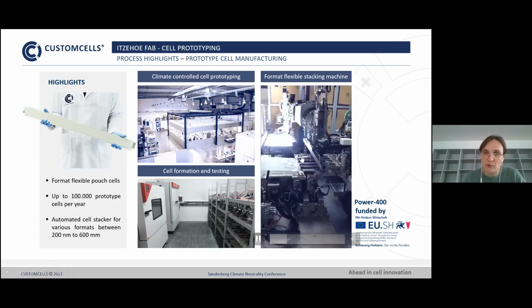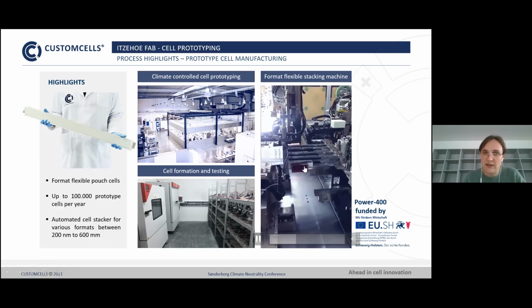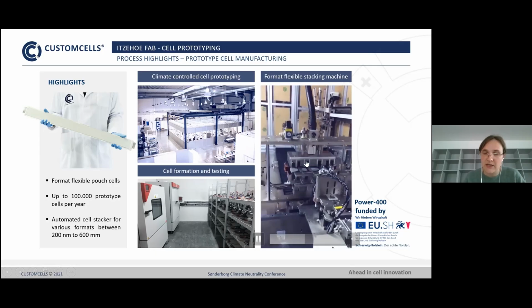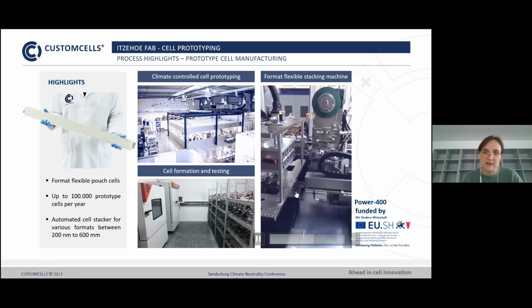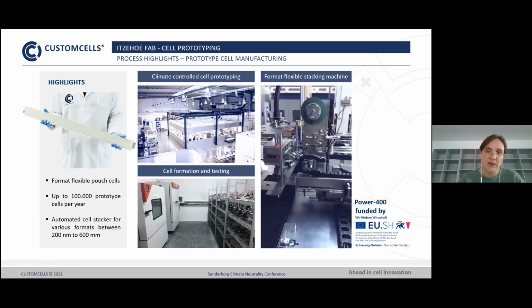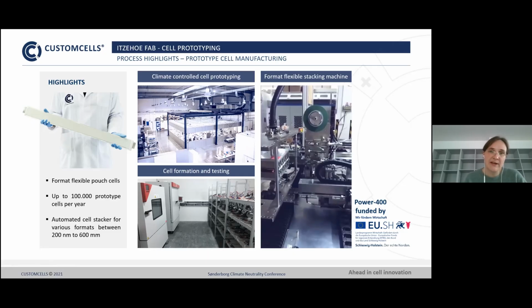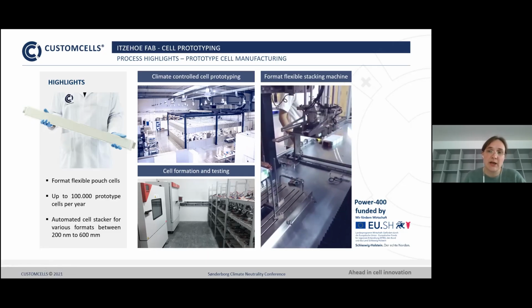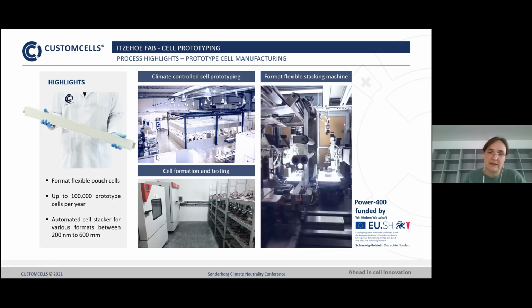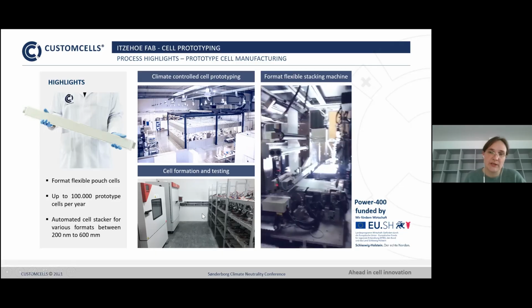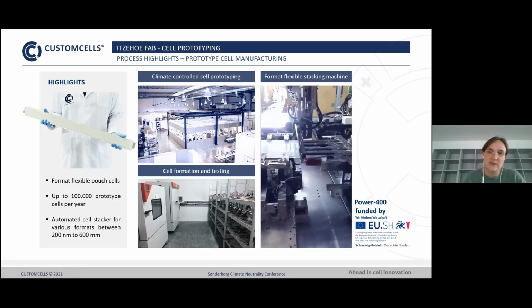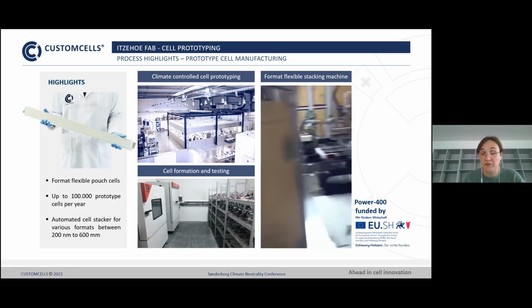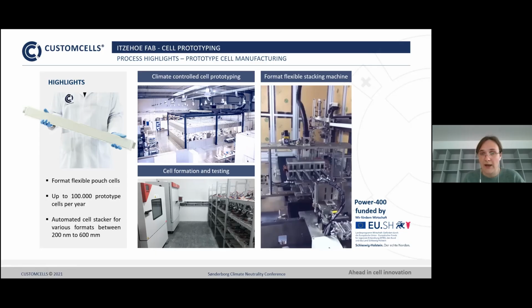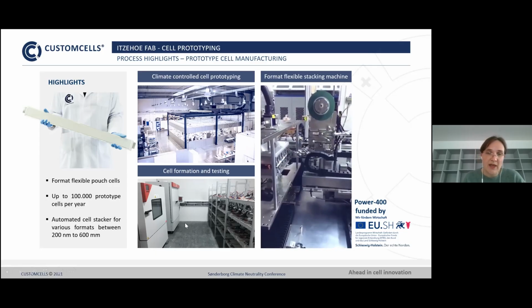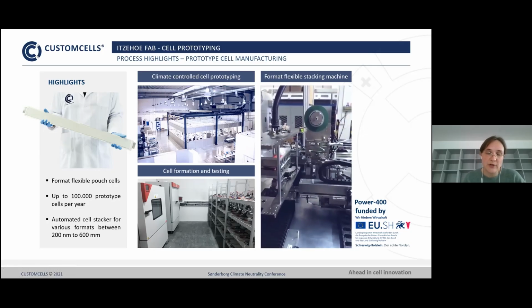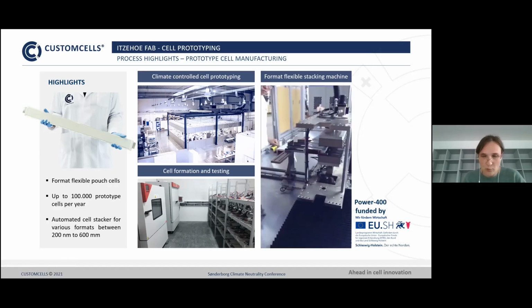When the stack is finished, the separator will just be cut through, so that you have now the stack, the anodes on one side, the cathodes on the other side, and then it will be taped so that the stack will hold together, and then you have your cell. We have a climate-controlled prototype production line, where the tabs are then connected to the terminals, and the cell is packed into a pouch. The pouch format is very flexible. That's why we are using it for our prototyping. After that, the cell is dried and filled with electrolyte, because the electrolyte is sensitive towards air and water.